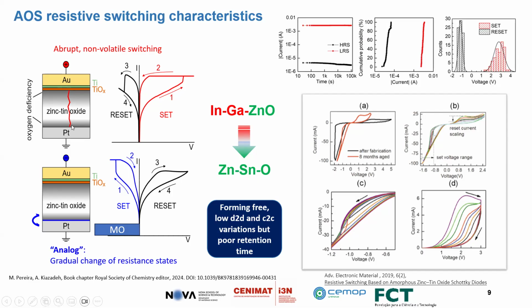You can tune it to a certain level of the resistance states, and normally the resistance change is abrupt. So the set is when you are applying voltage to go to the on state of the device, the low resistance state, and then reset is when you're coming back to the off state of the device. Of course, it's not just one filament, you can have multiple filaments and so on.